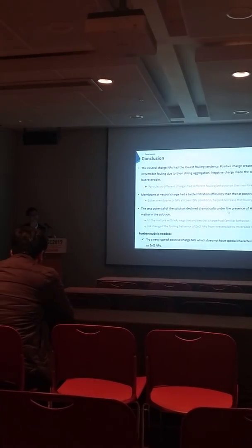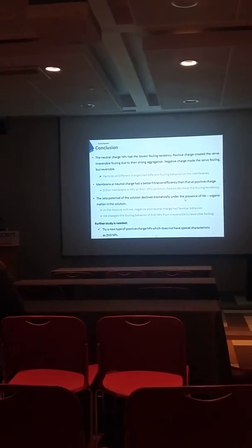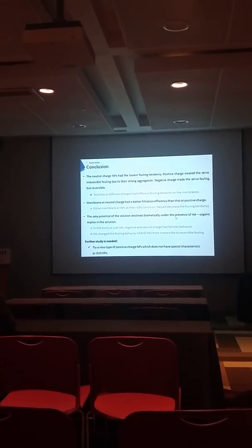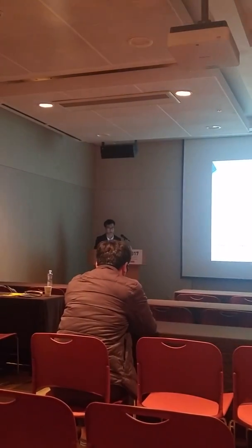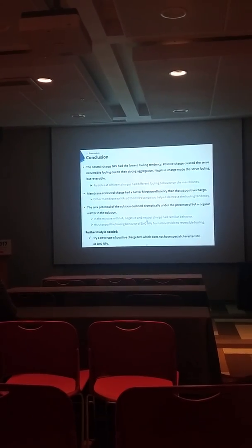And thirdly, when we put humic acid into the solution, the zeta potential of the solution transforms to negative. When we put humic acid together with the neutral and negative charge nanoparticles, the particles help to enhance the flux of the humic acid. And when we put humic acid with the positive charge nanoparticles, humic acid helps to transform the irreversible fouling of the nanoparticles into reversible fouling.